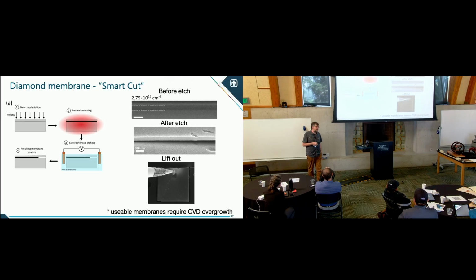And the nice thing about that is, silicon on insulator was one of the biggest achievements for silicon photonics, the ability to put thin silicon on top of insulator on top of more silicon. This effectively gives you diamond on insulator, so you can have diamond photonics integrated into materials. You can actually put this on SOI and then make diamond photonic devices out of it.